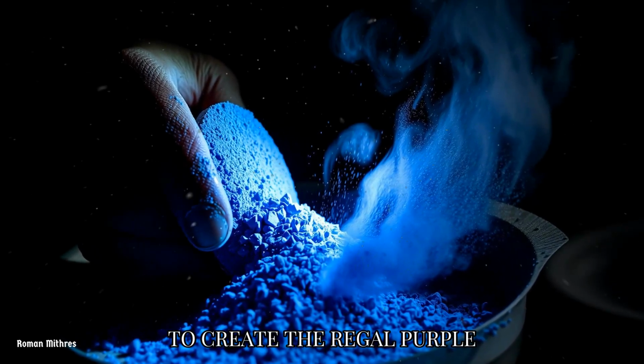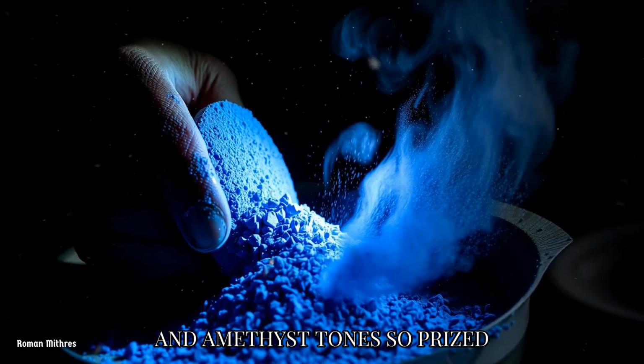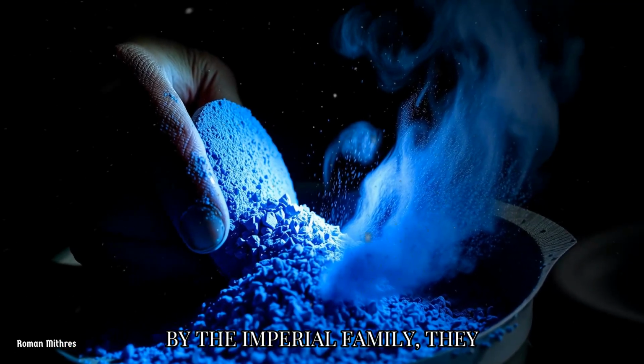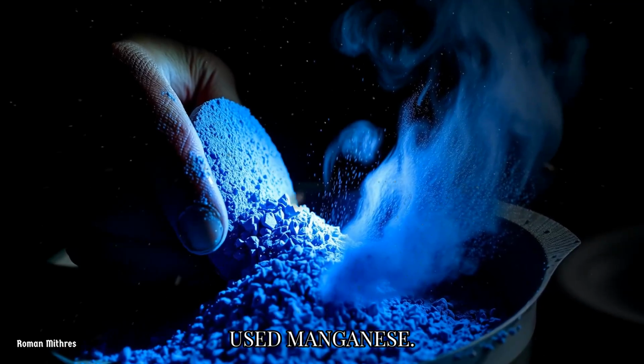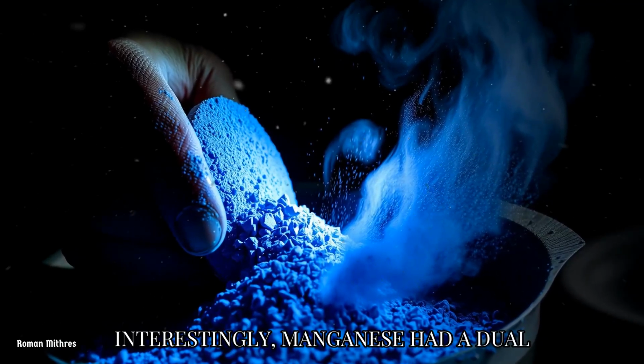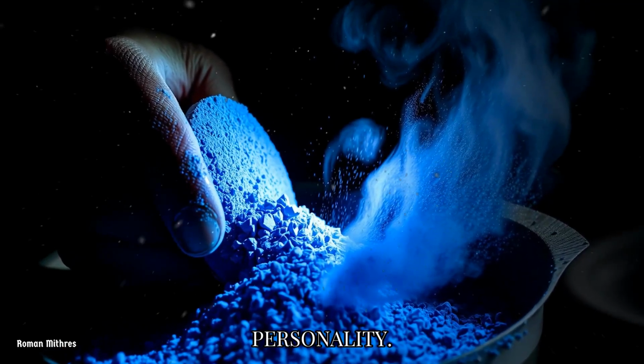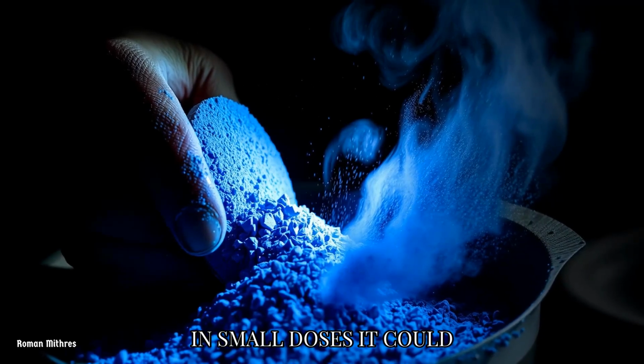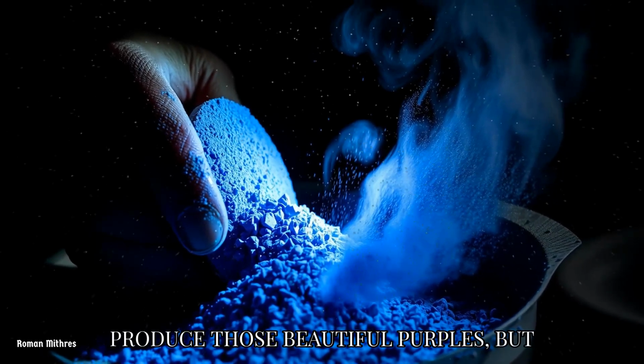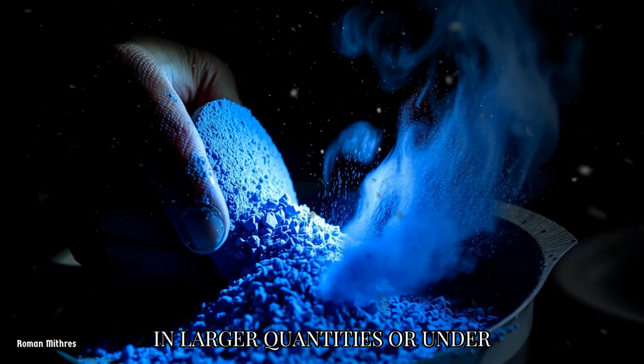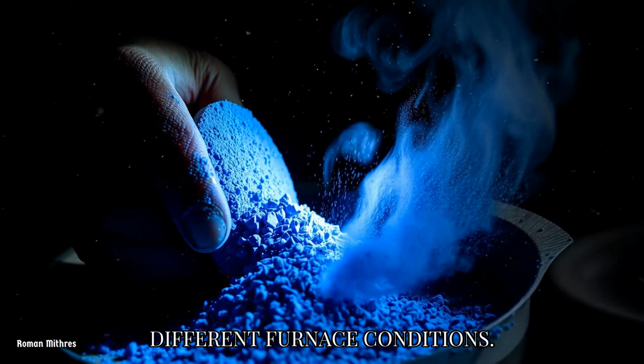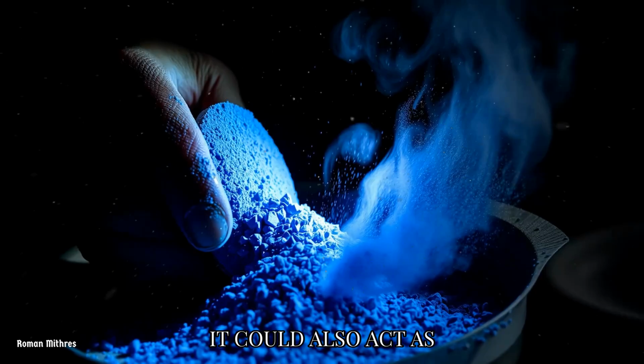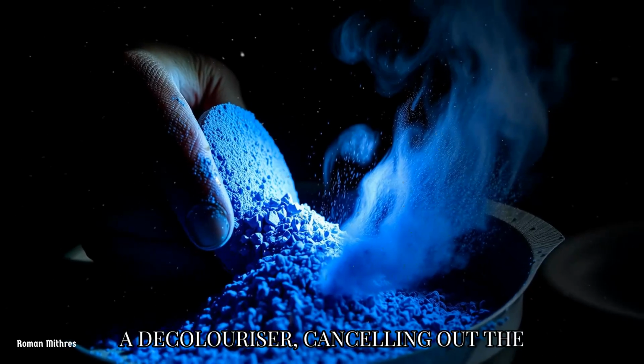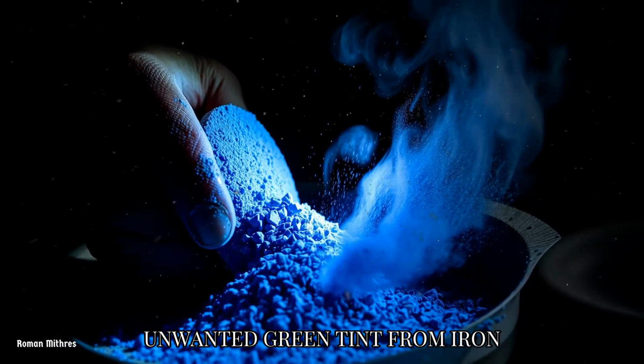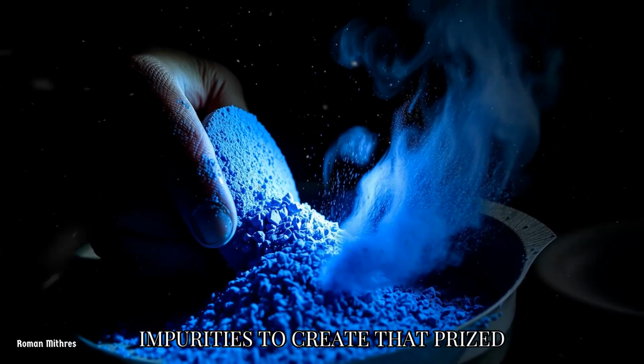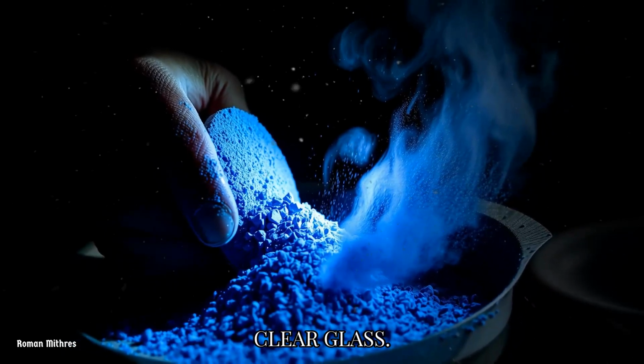To create the regal purple and amethyst tones so prized by the imperial family, they used manganese. Interestingly, manganese had a dual personality. In small doses, it could produce those beautiful purples, but in larger quantities or under different furnace conditions, it could also act as a decolorizer, cancelling out the unwanted green tint from iron impurities to create that prized clear glass.